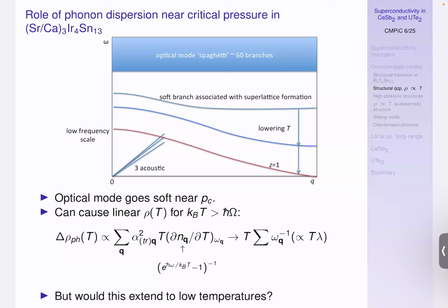Yeah, so the idea we put forward back then when we published these results was, well, okay, what's going on is there's a second order structural transition, which must mean that a particular optical phonon branch must get soft. This frequency goes to 0 at the transition temperature. And perhaps it doesn't just deform and go soft only at this Q vector, the whole branch might come down. And so now we have low energy optical phonons.